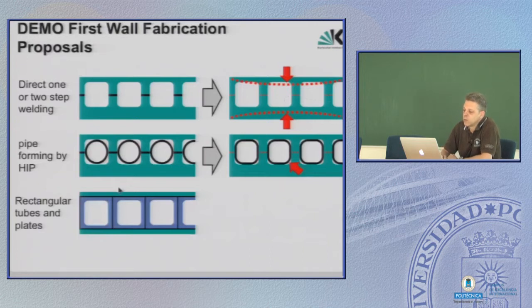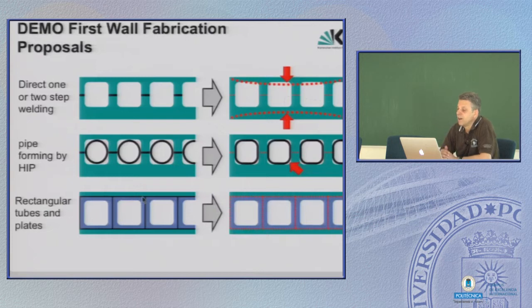Finally, you could go one step further. Instead of using this usual seamless tube, you could, with much higher effort and much more money, produce rectangular shaped tubes, take them together, and put two plates on top and bottom. Seems quite easy. Then you weld everything tight again under vacuum and put it in a hot isostatic press, and hopefully all these weld lines will be perfectly produced. The weld surface is much higher compared to the other studies, but it has been done. However, it did not work.